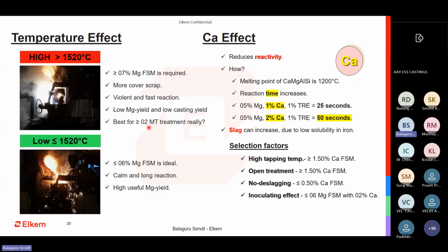So what do I need to do to ensure that the temperature loss is not there? Either I have a better insulation or I go for a ladle preheating setup, because the upside when I have both this ladle preheater and insulation is quite high. I can go for a low magnesium FSM. I can take the advantage of having smaller risers or riserless design. I can have lower addition rate of this low magnesium FSM. My casting yield is high. So the costing, if you back calculate it, the value is much higher. So again, low temperature is an ideal one.